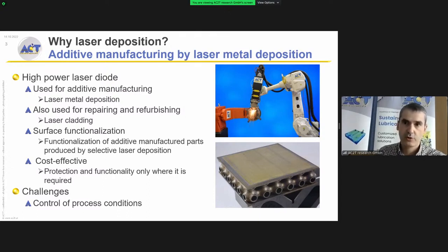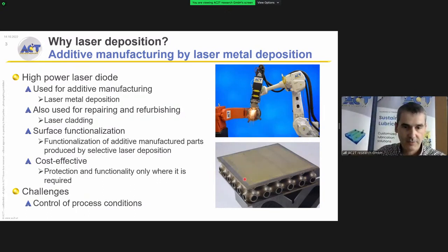When you use surface functionalization, it provides functionality only in those places where you need it, which also can be very convenient in many applications. And it also fits very well with other additive manufacturing techniques. For example, in this example here in the bottom, let me put the pointer. In this sample here, you can have a sample manufactured using, for example, selective laser melting, and on top of it, you can have a laser metal deposition for surface functionalization. So this is a very convenient method, very modern approach.